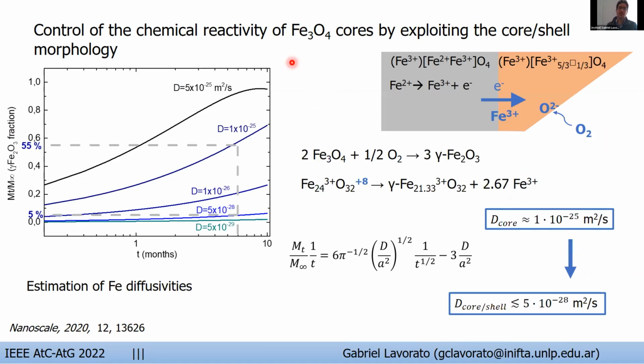So to interpret this result, we analyze the oxidation of magnetite to maghemite, which is a process limited by the cation diffusion in the lattice and can be described by Fick's second law of diffusion. According to our results, the diffusivities estimated by this model are reduced at least two orders of magnitude for the magnetite in the core shell sample. So this means that the core shell morphology can also be exploited to control the chemical reactivity of the magnetite cores, which is quite a promising result for this field.